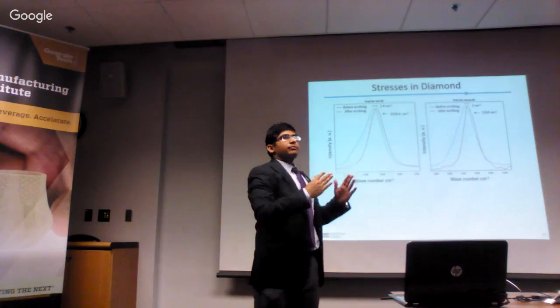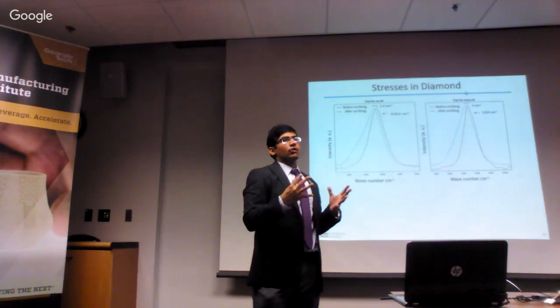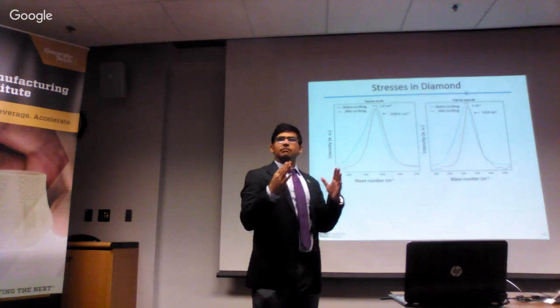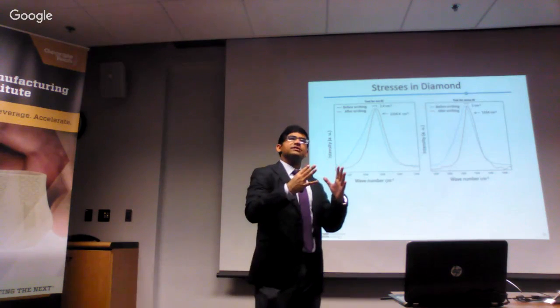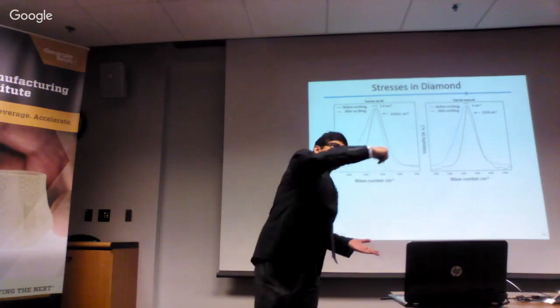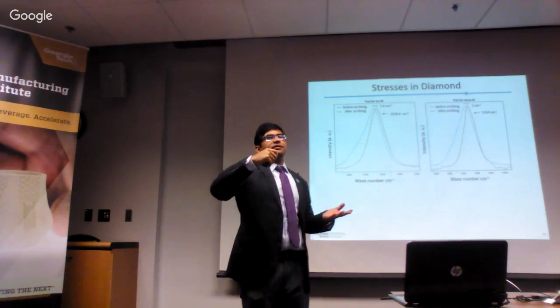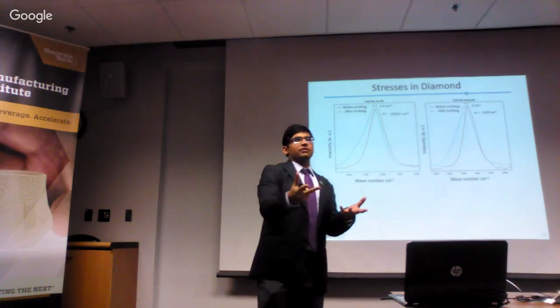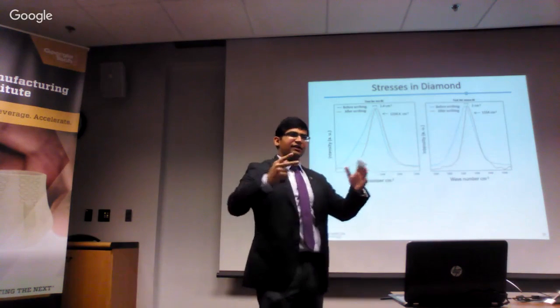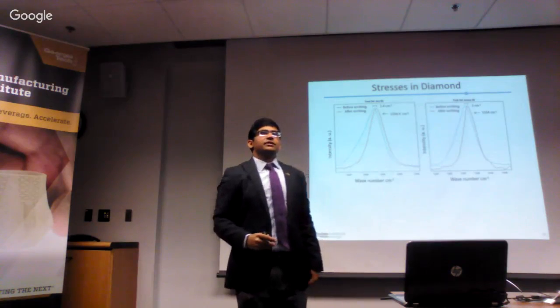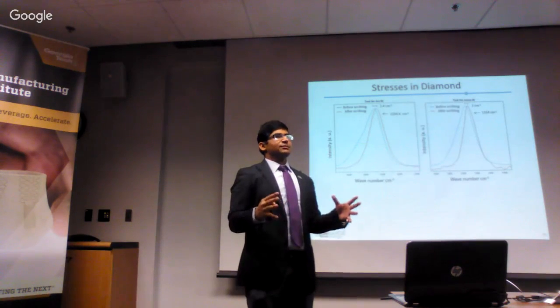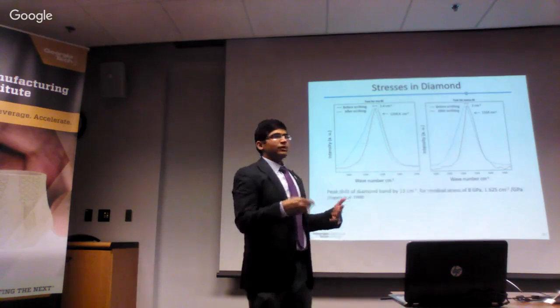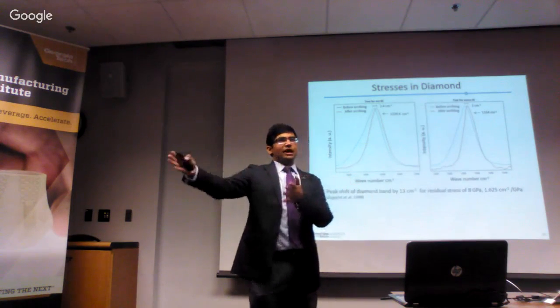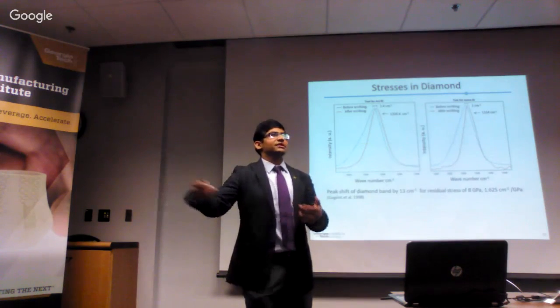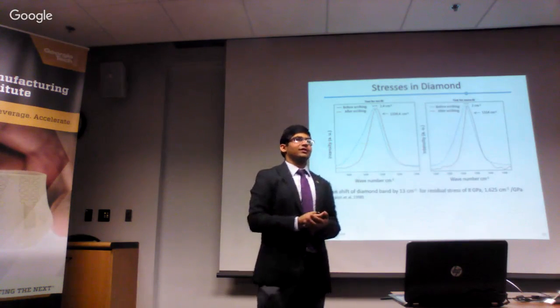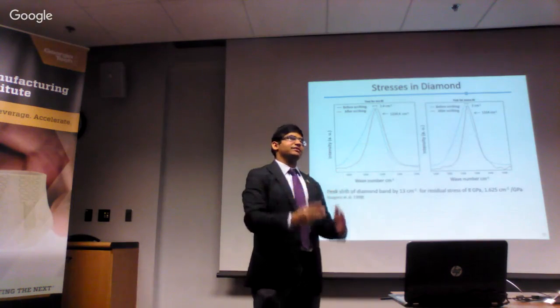When you say it's become narrower, the diamond might be getting more ordered. That might be because of the compressive residual stresses happening as the diamond is scribing across silicon. I understand the lattice is getting deformed, which is why the Raman spectra is getting more ordered. So most likely it is because of the compressive stresses. That's what we also find from the residual stresses having a rightward shift, which is compressive residual stress. So I think that is consistent with what you are saying, that the full width at half maximum is becoming narrower.